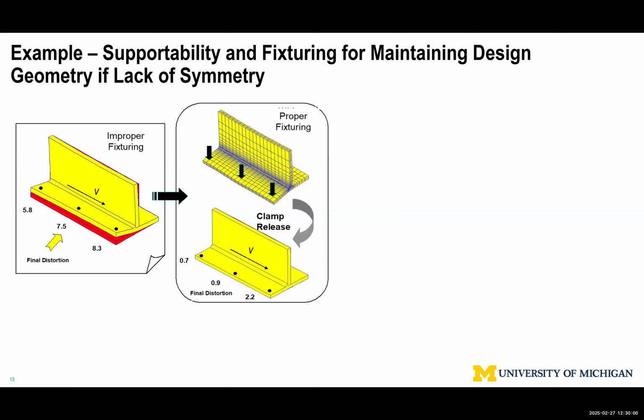So that means if you don't have symmetry, you have a problem. That problem has to be mitigated by smart fixturing. That needs supportability, and then you have to accomplish that stability by using additional means. In that case, we can use proper fixturing, which means providing clamping. Clamping has to be positioned in such a way as to produce uniform load distribution as close as possible to the action zone. The action zone is the plastic zone, located at the intersection. That means you want to be as close as possible. Too close interferes with the assembly process, so you have to compromise.